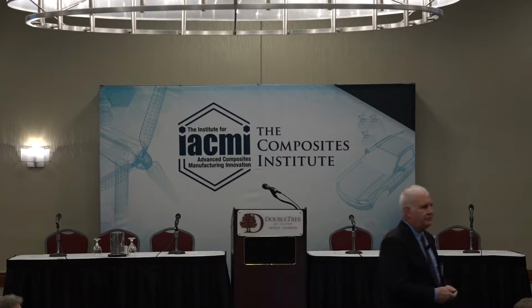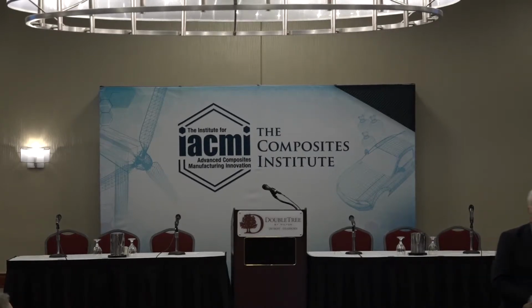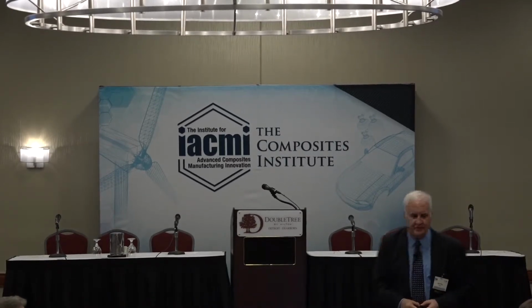Just a little bit about the short beam shear testing at Michigan State. They prepared these specimens using a wet winding process and the equipment here. They would take these samples, laminate them, and mold them to produce short beam shear samples where they measured the interlaminar shear strength. That's a good indicator of the resin fiber interface, and it was used to down select systems for further testing at UDRI. In addition to the vinyl ester systems, MSU also tested an epoxy system as a benchmark.